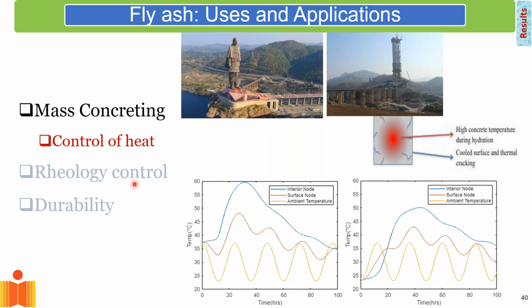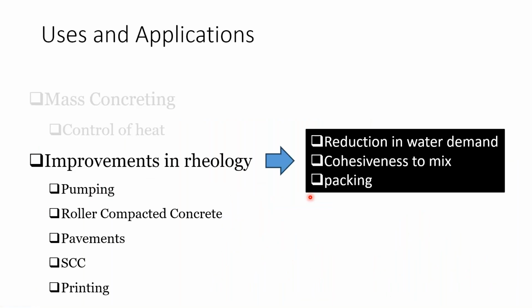So, controlling heat in mass concreting. Oftentimes I need to have material that is lower reacting. And here fly ash would be very beneficial in reducing the heat and therefore thermal cracking in concrete. Improvements in rheology: when I use fly ash in concrete, I produce a more pumpable concrete. It's because of those glass spheres that are present that act like ball bearings and improve the overall flow of concrete. Roller compacted concrete in pavements, SCC, and in concrete printing applications. Addition of fly ash actually gives some cohesiveness to the mix, helps with the packing, and overall helps in reduction of the water demand of concrete.